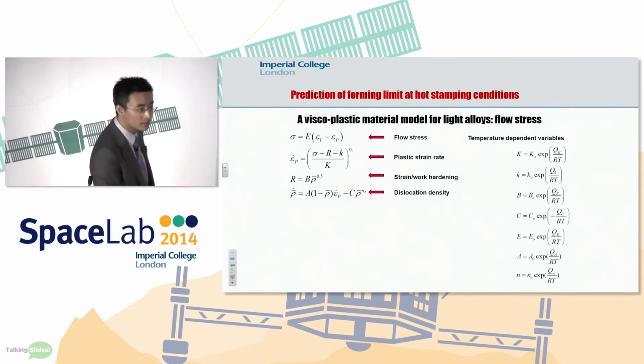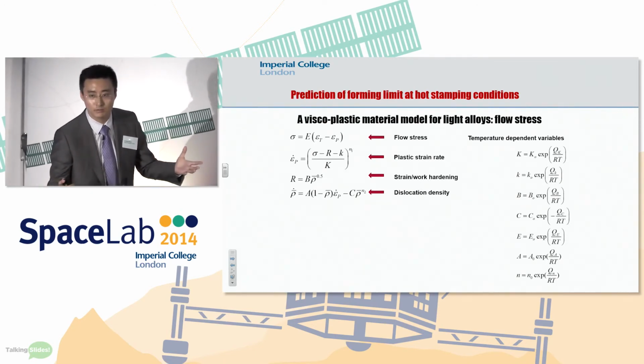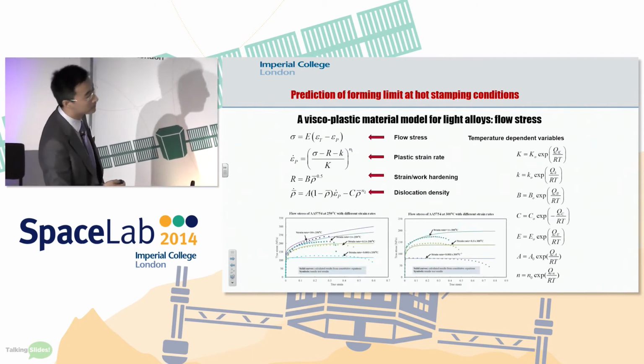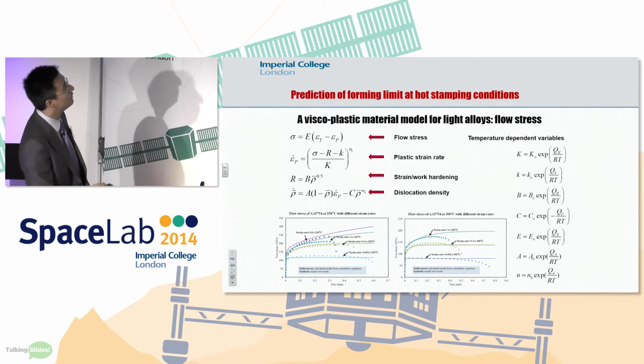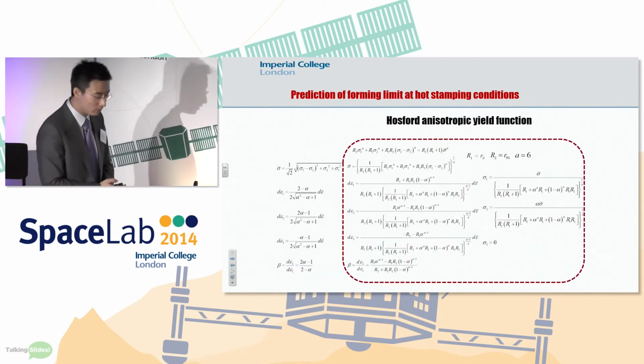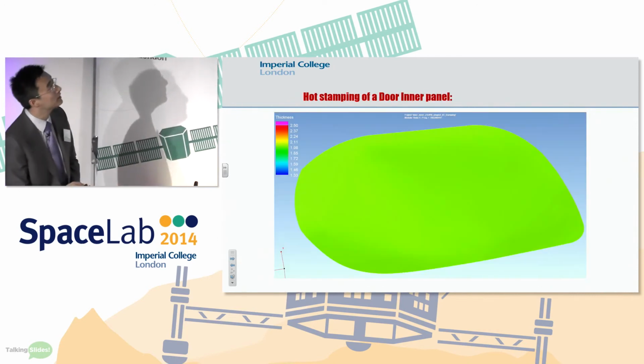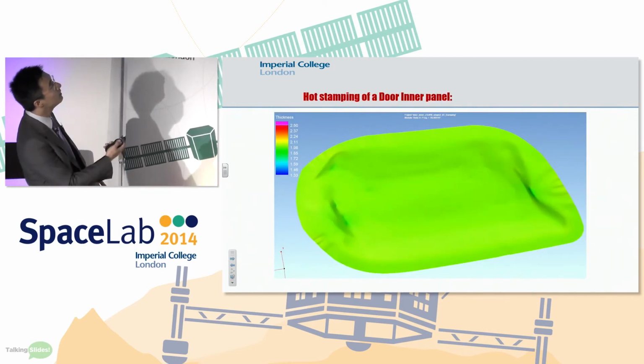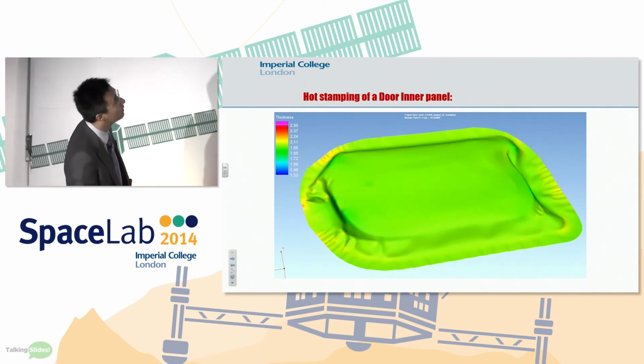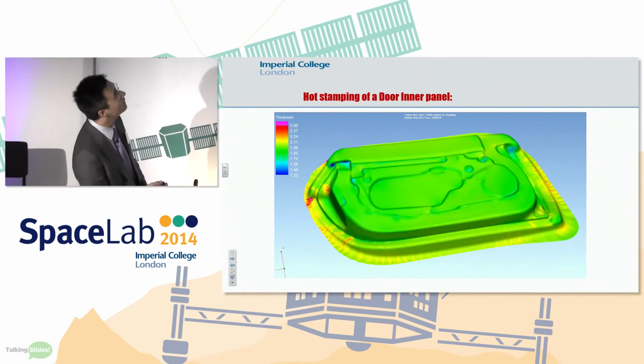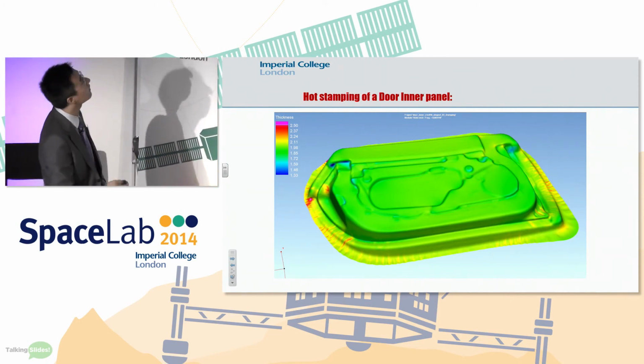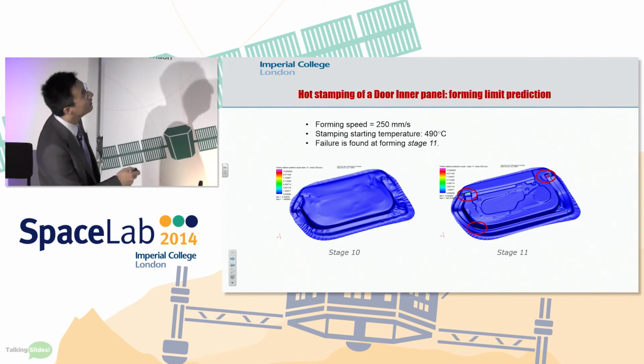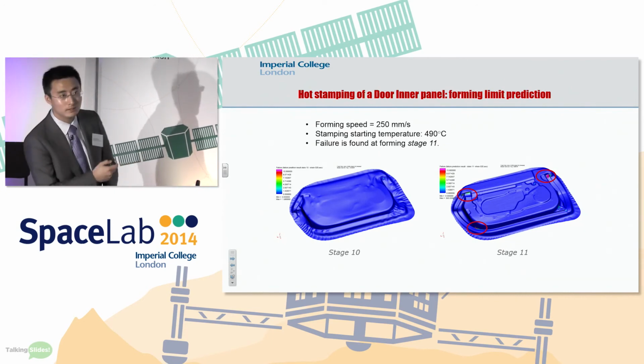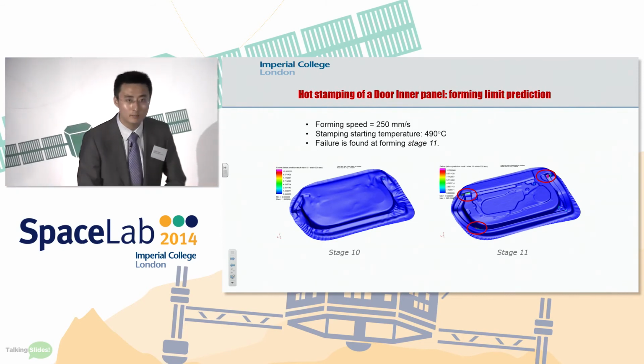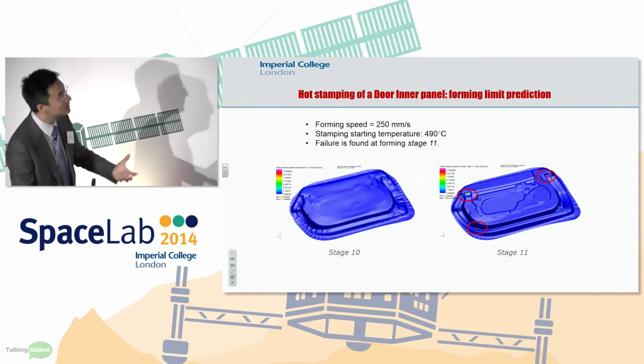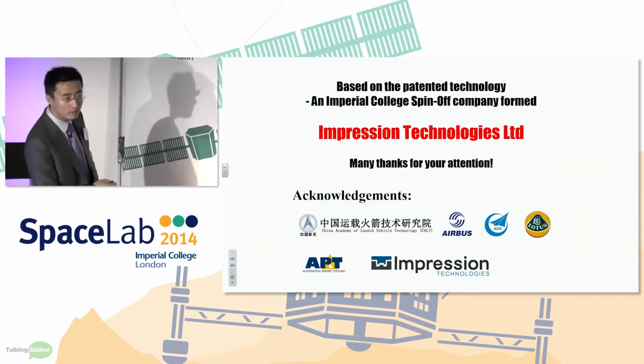And we developed advanced material models to capture the flow stress evolution at different temperatures and different strain rates. The material models are very accurate, and also we developed our own forming limit prediction model to predict the failure of the component. And this simulation result shows a very complicated aluminum component formed by using our technology. This is a door inner. And also by using our model, we can predict the failure. So if you have an idea to design a component, we can tell you how much deformation can be achieved by our technology.